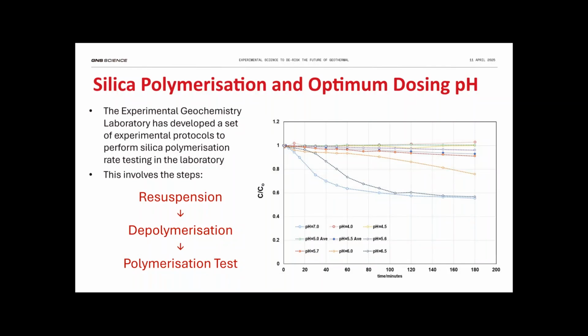So this is an example of a series of silica polymerization tests that were done on a real brine, a very high salinity brine. The brine was resuspended and depolymerized, and then these tests were done. And you can see this is a graph of the normalized concentration versus the time in minutes. So 180 minutes is 3 hours, which is a typical time for a polymerization test. You want to get the brine out of the power station, down the reinjection line, and down into the ground before silica starts polymerizing. So you can see at pH 7, which is the blue line here, we have polymerization.